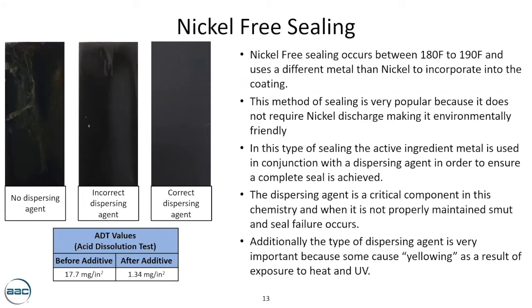And then, like you've seen in other slides, what you'll see in the ADT values here are, again, before the additive addition and after the additive addition, a significant drop in overall coating dissolution. Now, what I will say is that before the additive was made with this non-nickel seal, you'll see that it was at 17.7 milligrams per square inch. That was higher than even the hot nickel seal.